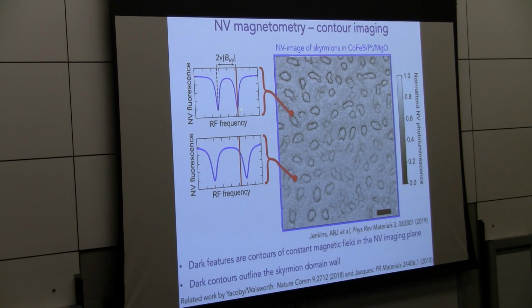And if it so happens that the local magnetic field brings the NV splitting into resonance with our microwaves, we see a dip in fluorescence, and we'll see a dark line. But if the magnetic field does not match the RF frequency, then we see bright fluorescence. In this case, we've arranged the magnetic field such that these dark lines are effectively contours of magnetic field, and they actually outline the exact position of the domain wall of that skyrmion. So at the domain wall, that's the field that we're resonantly tuned to. These odd-looking structures map the domain wall of the skyrmion.